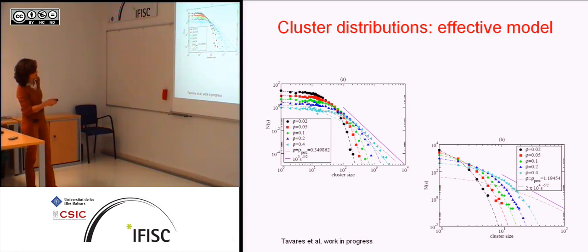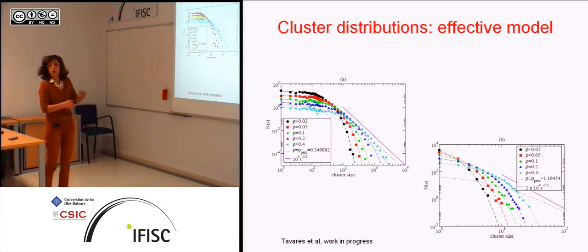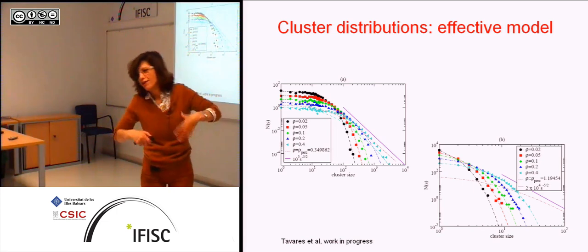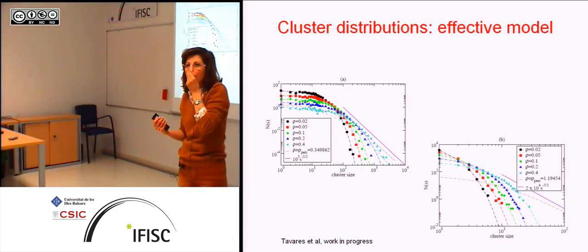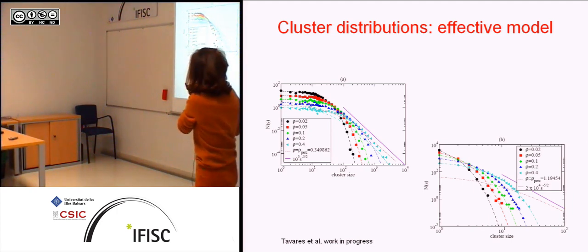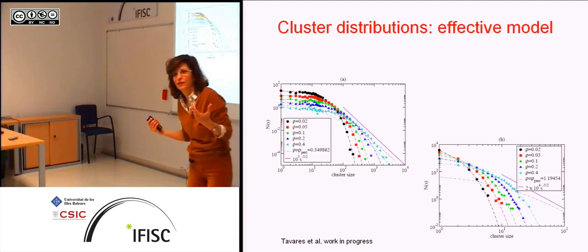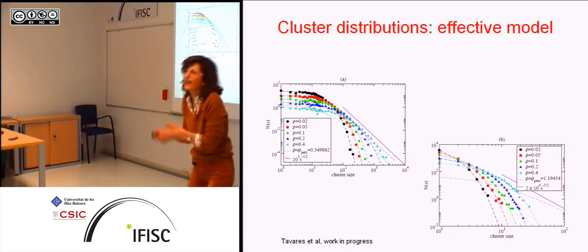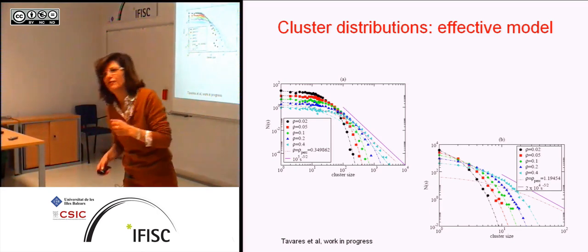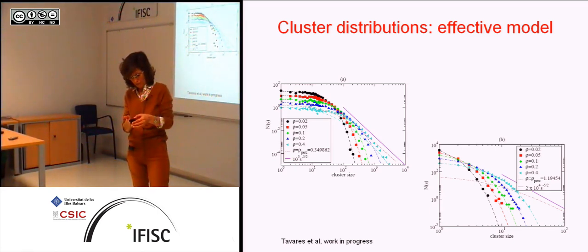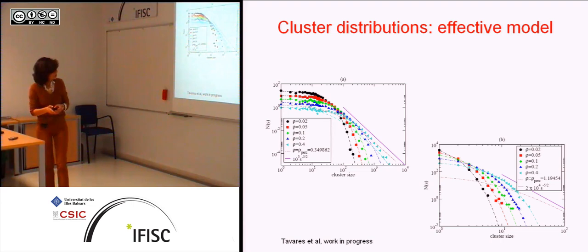This is beyond percolation, and everything breaks down. But below, we expect good agreement below percolation, because that's how the model is built. But we were a bit surprised that we got things right for small clusters, because the model is expected to be good for large clusters. And if you really refine it, of course it cannot be exact at percolation, because this is a no-loop approximation, and percolation in 3D has slightly different exponents. But it's also very good for the small ones, and I think we know why. I think that in these small clusters, the system actually has very few loops as well. It costs too much energy to bend the stuff. So this is really a no-loop type of approximation, and it seems to work too well. We don't understand all the details, and Zema didn't believe it, but it actually works very nicely. He did the calculations, so I'm not responsible for it.